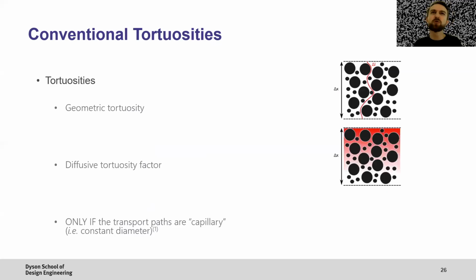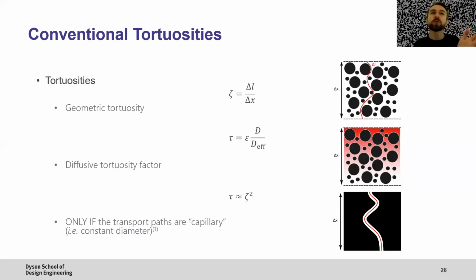Here are the 2 conventional tortuosity type metrics that people often see. The top one, geometric tortuosity, is a ratio of path lengths through an obstacle-filled system: the red line divided by the distance between the top and the bottom. Then there's the diffusive tortuosity factor, which is much more relevant to transport and says, solve the diffusion equation in this space and tell me how obstructed your flow was. And just occasionally, but almost never of relevance, there is a relationship between those 2 things. If your paths are nice capillary paths, then you can relate them, but usually not, certainly not in porous media.